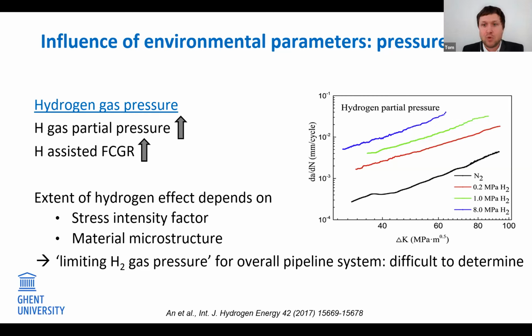Moreover, studies indicate that the actual extent of the pressure dependence on the fatigue crack growth varies with the microstructure again. These dependencies make it very challenging. Therefore, it is advised to perform a case-by-case evaluation of typical steel grades found in the system. Moreover, since fatigue testing is very time-consuming, labor-intensive and also very costly, the development of an adequate screening methodology based on relevant hydrogen characteristics can be of interest.